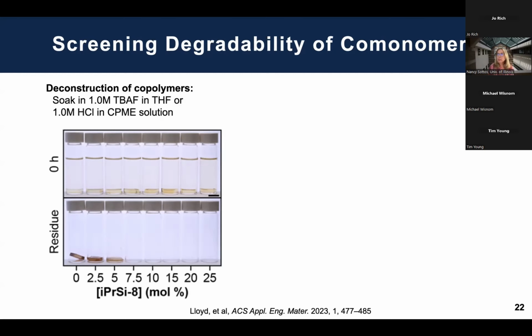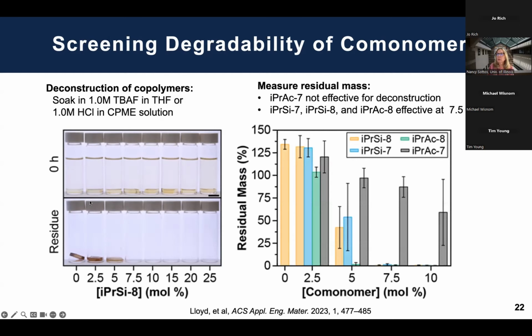And then as you move along with time, what you can see is that these materials with varying amounts, this is actually after 16 hours. I don't know where the 16 hours disappeared to on here. You can see that with 5 mole% of the cleavable comonomer, you get full dissolution of the thermoset network, which is quite extraordinary. And on the right, you see just plots of residual mass as a function of comonomer.